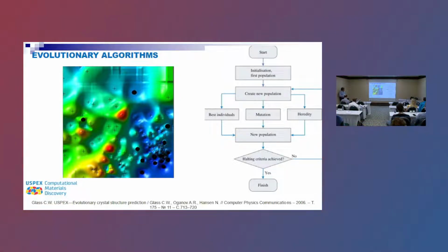We use a so-called evolutionary algorithm. It means that we put in the first structure and calculate the energy. After that, we make different movements, shifting the atoms a little bit by some algorithm, flipping, and so on. Basically, we are considering a multidimensional space of the energy, depending on the distance of titanium and selenium. Of course, it can have mountains, it can have low energy states, and we are trying to find them.